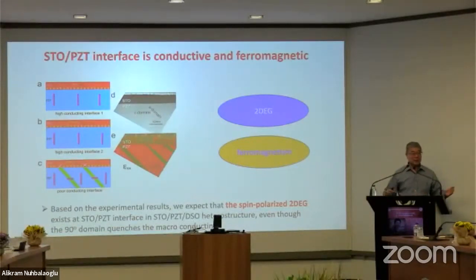But the question is why so many studies on ferroelectric structures already showed that the interface between ferroelectric and insulator is insulating. The reason is that the films or bulk materials people measure always include different kinds of domain walls. For this kind of domain wall, you have a conducting electron gas. But if you have a 90-degree domain wall, the polarization is parallel to the interface. There's no bound charge at the interface or surface. Therefore, no 2D electron gas or 2D hole gas exists.